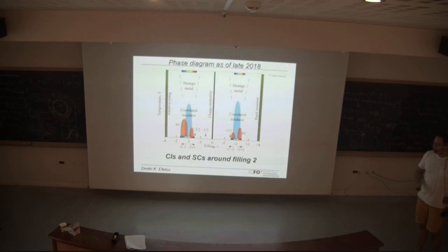And then what was observed as of last year was that at a filling of -2 and +2 electrons per unit cell, correlated insulating states were observed. So we observe very resistive states, and we can extract a temperature activated gap. The main evidence that these are correlated insulating states is that they come at integer fillings of electrons, and the evidence that it's an insulating state is that we can extract a temperature activated gap at low temperatures.